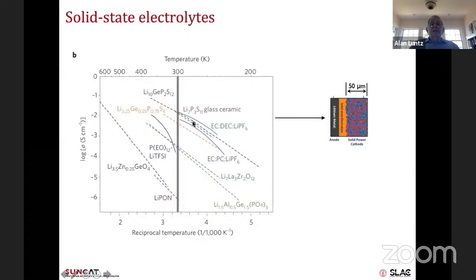So most of the concentration and a lot of this work is being done in startup companies. So we don't know exactly what they're doing, but I think most of them, or many, are using the sulfides because you need this kind of a conductivity roughly to get a very high capacity battery with thick electrodes. On the other hand, some companies and much research is going on in, say, this material, where you can make a stack of thin film batteries, which would also give you high capacity. At any rate, it looks like there are materials with enough lithium-ion superionic conductivity to build batteries with.